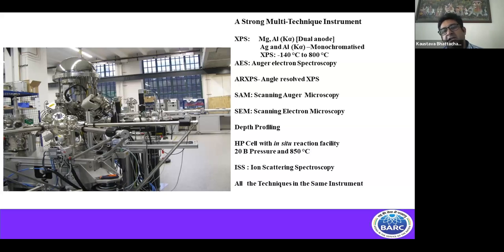As we can measure the kinetic energy of these ions after elastic scattering, and as the ions are much heavier than the electrons, we can measure how they interact with the surface. So this ISS is far more surface sensitive. It gives results up to 2 nanometers rather than 5 nanometers.